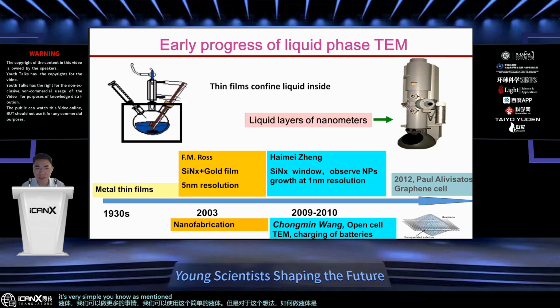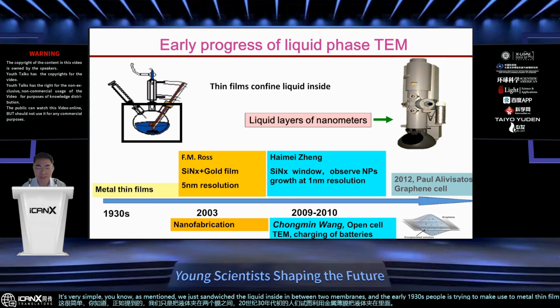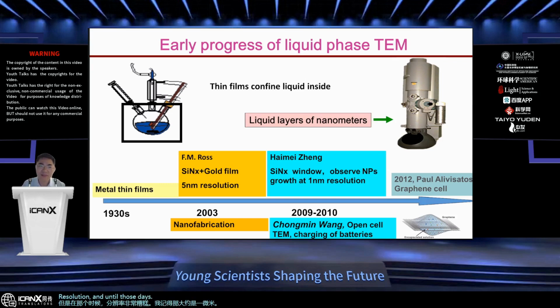The idea of how to prepare a liquid sample is very simple. As mentioned, we just sandwich the liquid between two membranes. In the early 1930s, people tried to use two thin metal films to sandwich liquid, but the resolution was very bad, about 1 micrometer, as I remember. Then in 2003, Frances Ross, who is now at MIT, developed the modern silicon nitride based liquid cell. With her design, it could reach 5 nanometer resolution. Later, Haimei Zheng developed a new liquid cell design and improved the resolution to 1 nanometer.